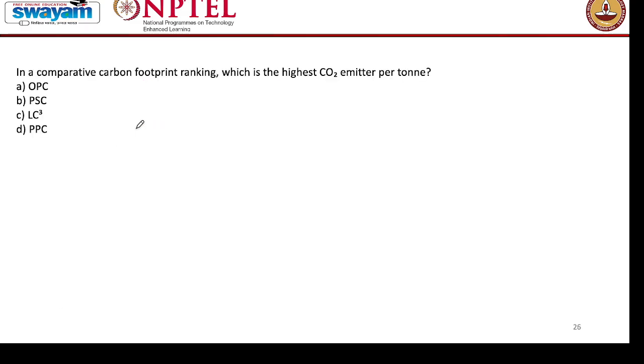Next question: in a comparative carbon footprint ranking, which is the highest CO2 emitter per ton? Now we know that the lowest one is the one in which we are replacing the most clinker content, which could be LC3, PSC, or PPC, depending on the replacement level. Typically, LC3 is considered as having the lowest CO2 footprint. The maximum footprint is from the OPC, which is the typical cement used in the last 100 years. But there is a problem of CO2 emissions, hence we should go for blended types of cements.